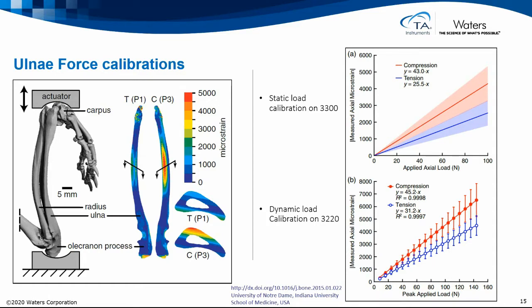And because we have calibration curves, we can then understand how much strain was actually on that bone for that specimen. In this case, there's a subtle difference between static load calibration and dynamic load, which is a nice thorough investigation because what you'll see is the loading that they'll actually apply is a dynamic load. So it's important to understand the strain calibrated in that environment.